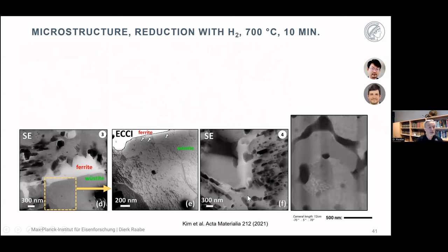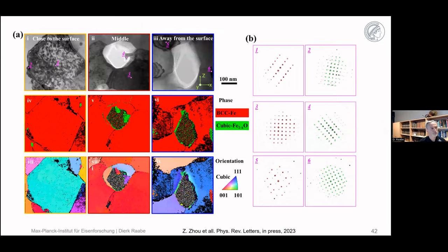When you look into the microstructure, you see in part, in this picture here, that not the entire remaining wüstite is surrounded by iron, but you have delamination and fracture also, which is very good for removing the water from the reaction point. You will see that later in more detail. That means we study the details in electron tomography of this porosity that is being formed and the role that it plays for the removal of the redox product.